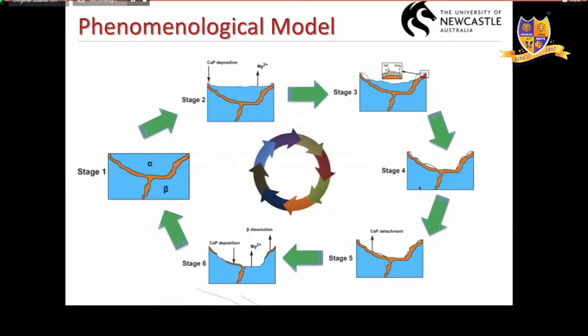So we proposed a model: the formation of calcium phosphate, dissolution of the beta phase, forming of the calcium phosphate, and how the calcium phosphate dissolves. There are about 6 stages, and it goes around. It's a cycle. So ultimately, at the end of the day, your whole alloy is dissolved, right? So that's good news. But as I said, the localized degradation is a problem, because that can affect the mechanical integrity of the implant during service.